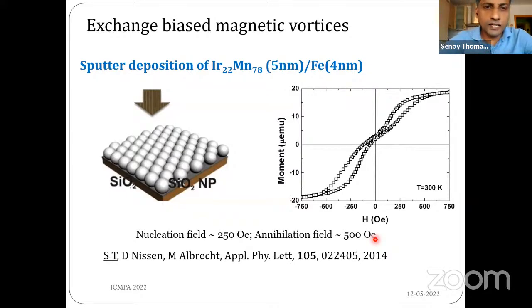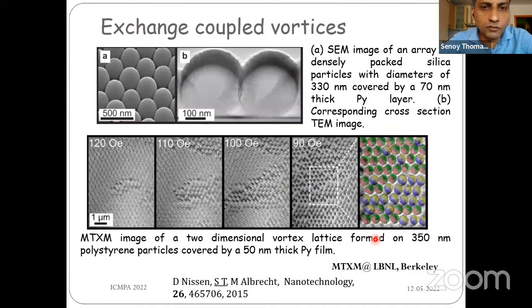Okay, we also did a series of experiments by changing the thickness of the magnetic nanocaps. What we found is that if you increase the thickness to, for example, 70 nanometer, then there is a good possibility for the coupling of the nearby magnetic vortices. We call these exchange coupled magnetic vortices. In order to understand the magnetization reversal in those exchange coupled magnetic vortex arrays, we did magnetic transmission X-ray microscopy. What we found is that the reversal process is via the nucleation of a collection of magnetic vortices rather than individual nucleation of magnetic vortices.